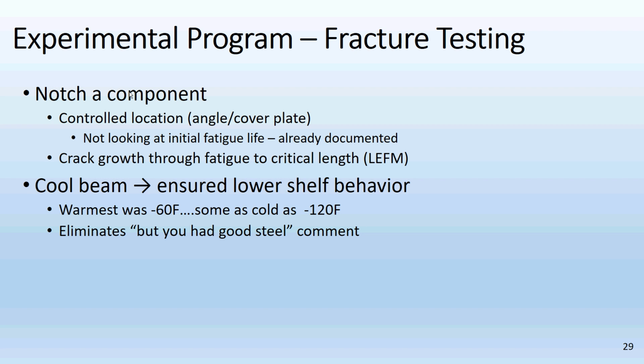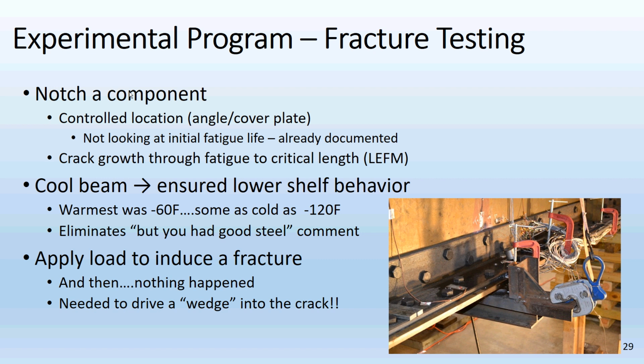That led to maybe trying to be a little clever on how to get failures to occur. What we wanted was for very little cracks to become unstable, to fracture, to get the bang, so to speak. And you'll see a video later where the explosive fracture occurs. That led us to cooling the girder, notching the girder, getting a crack, cooling the girder, and then driving wedges into the crack. Obviously completely unrealistic, right? The girder's up at like 0.55, 0.65 Fy. It's at minus 110 degrees, and then we drive wedges into the crack, but that's what it took to get the fracture to occur, and then evaluate, could the girder explosively fail?